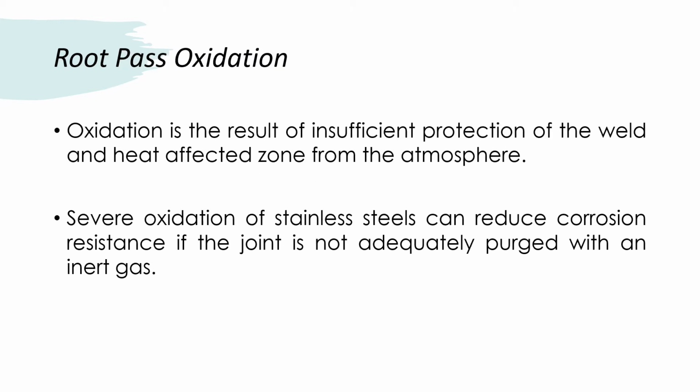Next is the root pass oxidation. Oxidation is the result of insufficient protection of the weld and heat affected zone from the atmosphere. Severe oxidation of stainless steel can reduce corrosion resistance if the joint is not adequately purged with an inert gas.